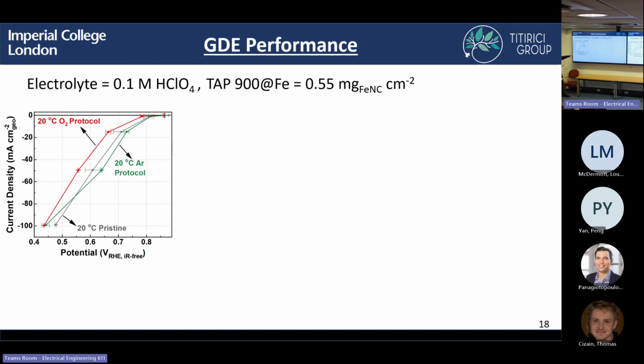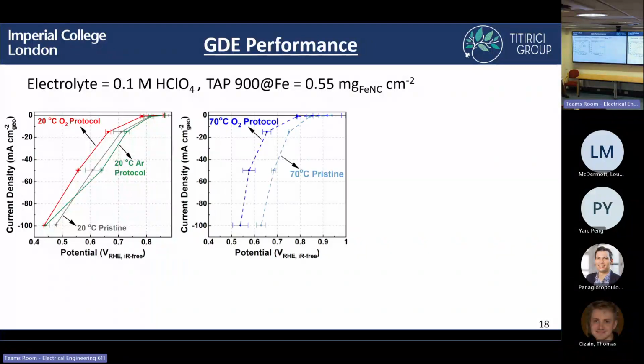Whereas in oxygen, we can very clearly see that there seems to be some degradation of the catalyst, as we see the potential for the same current density is shifted by around 50 millivolts. And then looking at the measurements, sorry, this should say 70 degrees, we see, as you would expect, for the pristine material, performance is better at high temperature, but we have even more severe degradation of the catalyst, as we see the potential shifting by more than 50 millivolts.